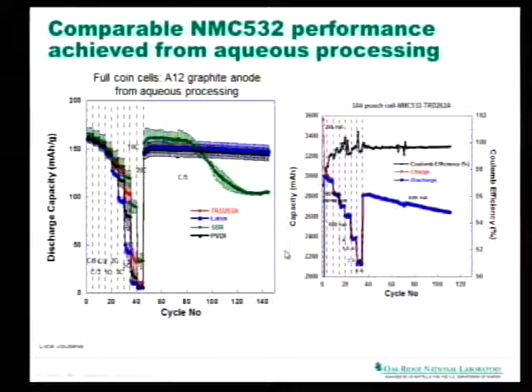And on the coin cells, the black curve is the benchmark. That is the traditional NMP processed material. And it's right in the ballpark of where the other colors are, other than one particular set of binders. This is a study of which binders should we use for that material. And we had some problem with one binder, but the other two are right in there. We have no issues.